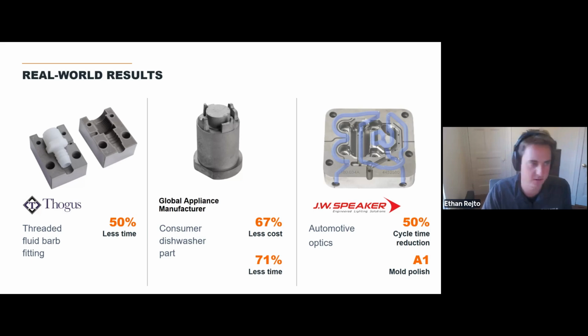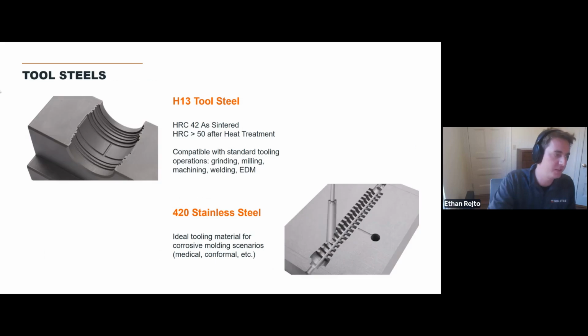And then this is very common to talk about with metal 3D printing and molding: conformal cooling. An example of an automotive optic component where they got a 50% cycle time reduction thanks to conformal cooling. And they were actually able to achieve an A1 polish, which, if you know about optic molding, the finish of the mold is very, very important to get that very clear finish, which they were able to do off of the Mantle insert.